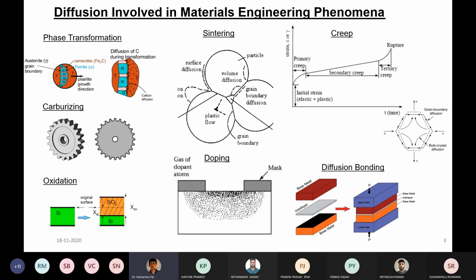So putting one carbon in the interstitial position of a FCC phase like austenite creates less elastic strain imbalance, because it is going to take the position inside the octahedral voids. Those octahedral voids are symmetrical voids. So in symmetrical voids, the elastic strain and asymmetry nature will be very less. So with respect to stability of the structure, the contribution will be high. So that's why austenite can accommodate more percentage of carbon.